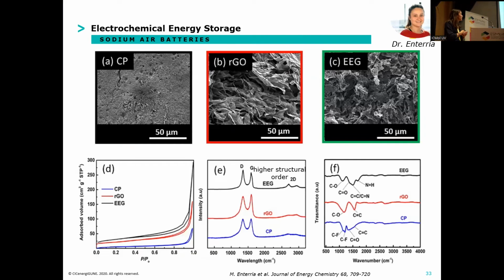So another example that we studied was to compare the currently used carbon paper, normally used in fuel cells. It's a carbon electrode, and on the top a gas diffusion layer that is porous carbon with binder. Then we have this reduced graphene oxide that in this case was from commercial graphene, and then we reduce, and then we freeze dry to produce aerogels. And then we have electrochemical exfoliated graphene.